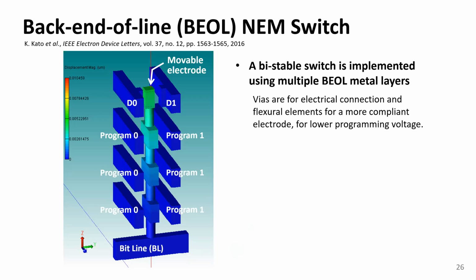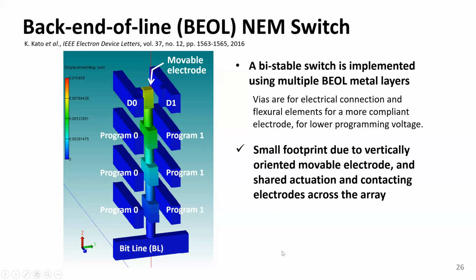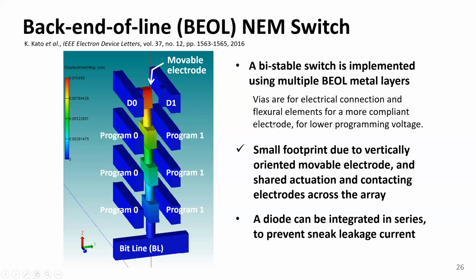So shown here is an example of a single pole double throw switch design implemented using multiple back end of line interconnect layers and via layers to form a conductive movable electrode. The actuation electrodes on either side of the beam are formed from the lower interconnect layers, and they are used to electrostatically actuate the beam to the right or to the left into contact with data line electrodes in an upper interconnect layer. Now, the vertical orientation of this movable beam provides for a more compact footprint and is conducive to implementation in a cross-point array architecture. So the footprint of this reconfigurable interconnect can be smaller than that of an SRAM cell. And finally, since the back end of line NEM switches are implemented in layers over CMOS devices, it's straightforward to integrate a diode in series with each movable electrode to prevent sneak leakage current in a cross-point array, which I will show in a subsequent slide.